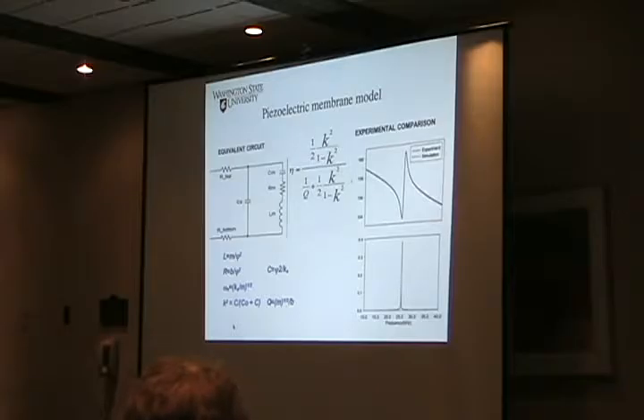What's the thickness of the gas layer? The thickness of the gas layer or the cavity itself? In the gas layer in the cavity. The total cavity thickness is on the order of about 40 microns. We vary between 25 and 50. We use a wicking structure to bring in fluid, so the fluid's about 1 micron thick. When we evaporate it, it has a hot side, and the cold side recondenses up on top. So the thermal penetration depth is much bigger than the thickness of the cavity. Yeah. So you're in the isothermal limit.